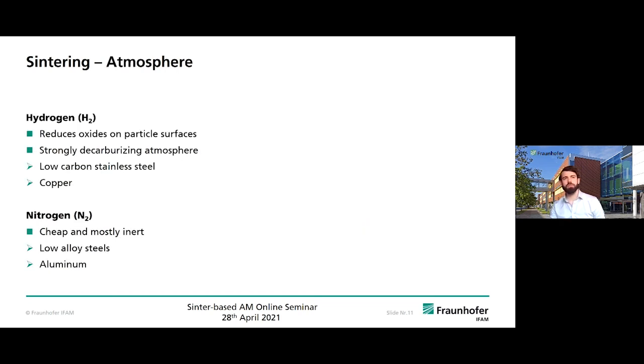When going to the process atmosphere, first of all, there's hydrogen to mention. It reduces all oxides on the particle surfaces and also strongly decarburizes the material. So you can't use it for materials with a certain carbon content that you want to keep. Low carbon stainless steels and copper are appropriate materials for hydrogen. Another atmosphere is nitrogen. It's cheap and mostly inert and is suitable for low alloy steels as well as aluminum. One positive thing about these atmospheres, and that's their advantage, is that they are soluble in the metal lattice, so this gas can go through the material itself.